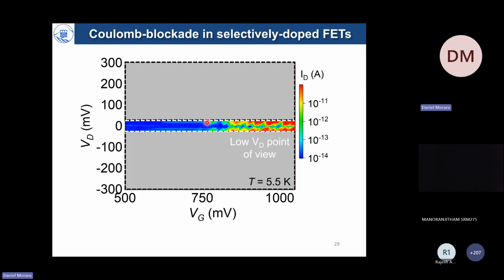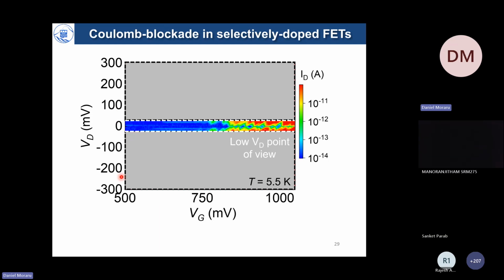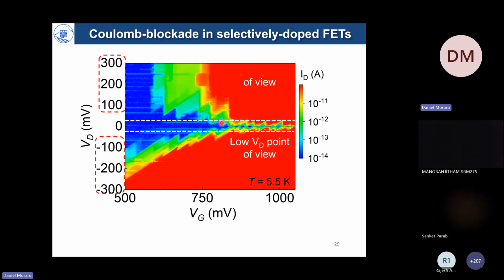However, we had a feeling that there must be something hidden in this noise level region. And for that, we increased the VD to values which are not usually measured. And when we measured in a wider range, we could actually observe extra Coulomb diamonds with a little bit of a peculiar shape, and which are not closed. These are open diamonds.